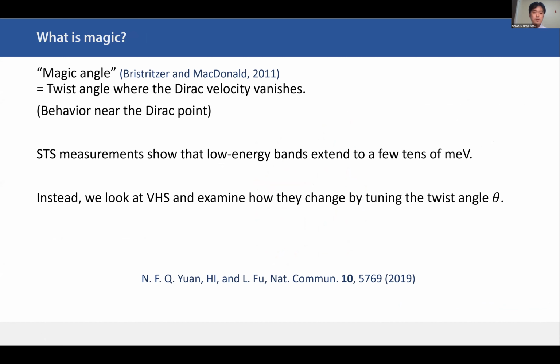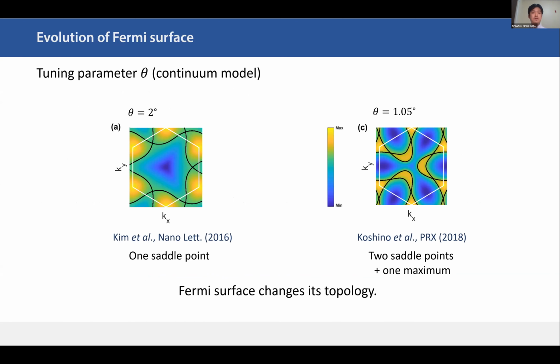So instead, we try to look at the Van Hove singularities and examine how they change by tuning the twist angle theta. And from this perspective, we want to redefine the notion of magic angle. Okay, so let's again look at a continuum model for twisted bilayer graphene and change the twist angle to see how the Fermi surface topology changes. At a relatively large twist angle of 2 degrees, we see a simple triangular Fermi surface in this hexagonal Brillouin zone.